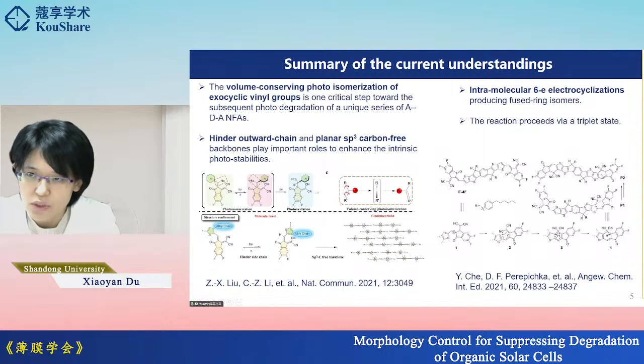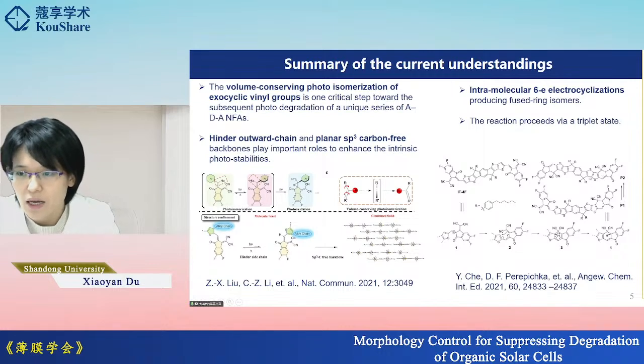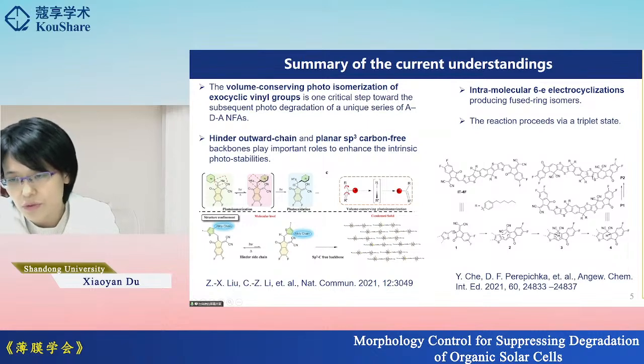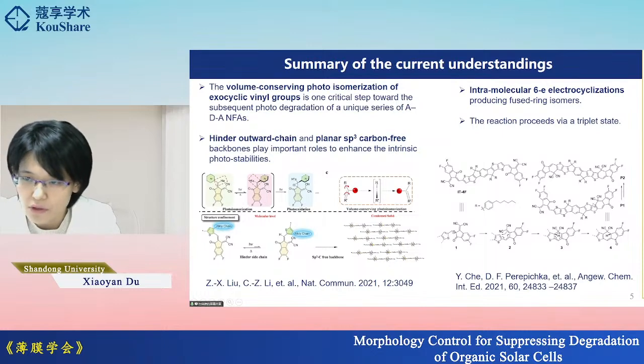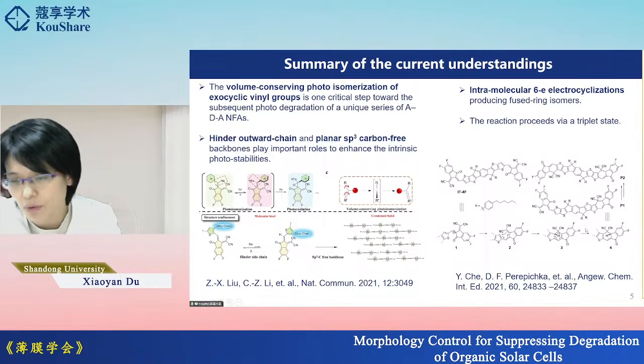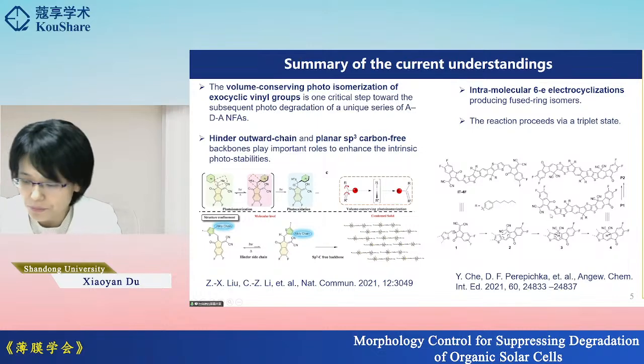6π electrocyclization, producing this kind of fused ring isomers. And this can happen without the presence of oxygen and only under illumination. And the triplet state is very important during this photoreaction.